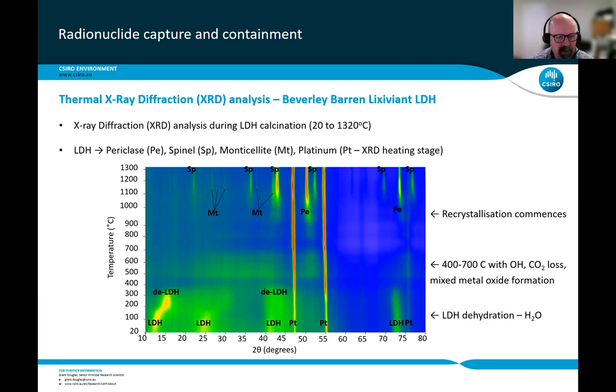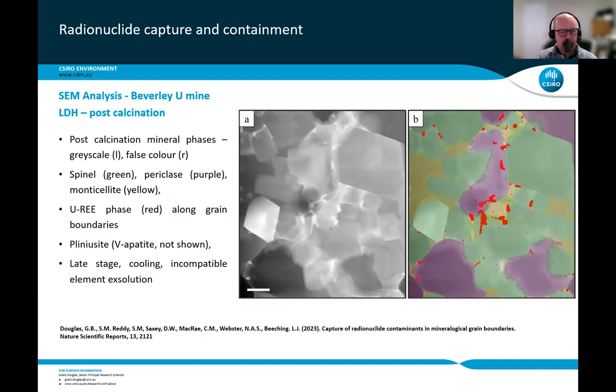We start to see periclase forming, periclase being a magnesium oxide, so that's the first phase to form. But after that, we then start to see monticellite forming, monticellite being an olivine mineral, and also spinel, spinel being an oxide mineral, in this case, an iron alumina oxide. So above 1,000 degrees, you get lots of these recrystallization reactions occurring. And this is where the really interesting stuff starts.